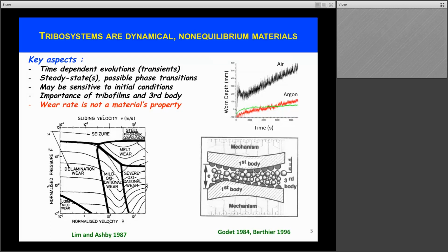Furthermore, we may start with a pair of bodies in sliding contact, but very often at the interface between the contacting asperities of the two first bodies, something else will be formed. This something else is what is often referred to as the third body, or tribofilm, or tribolayer. And there are many conditions where the wear behavior is largely dictated by what's happening in this third body. All these aspects make it difficult to predict wear resistance.